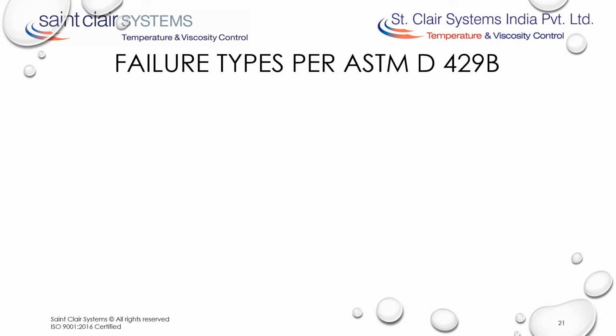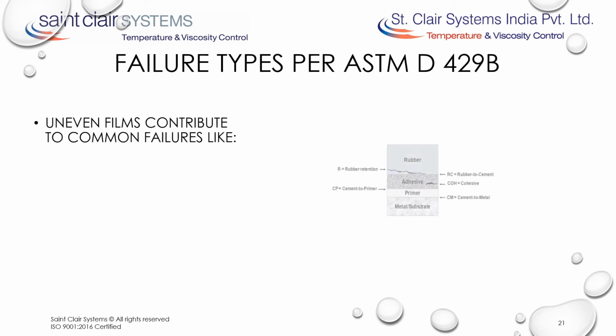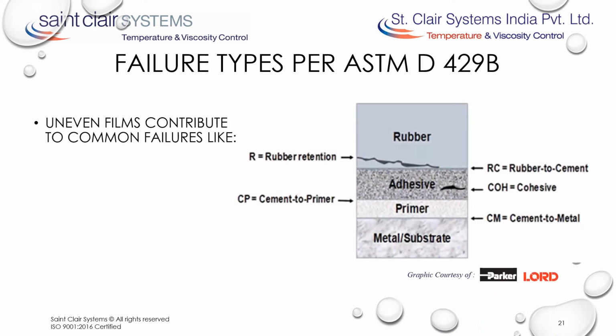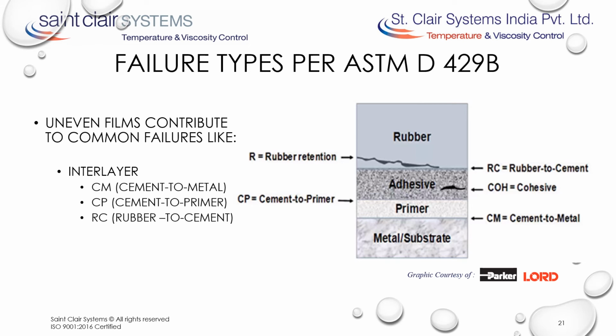So, what defects can we attribute to these temperature-induced changes in Chemlock and primer viscosity? The same ones you're used to. First, there are the interlayer failures. These are the result of poor bonding between the substrate and the primer and the Chemlock and the rubber. Then, there are the intralayer failures, often defined as cohesion failures. It's easy to see how these relate to our temperature-induced film variations.